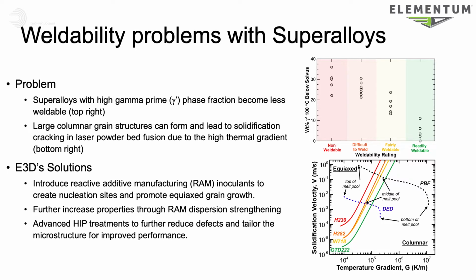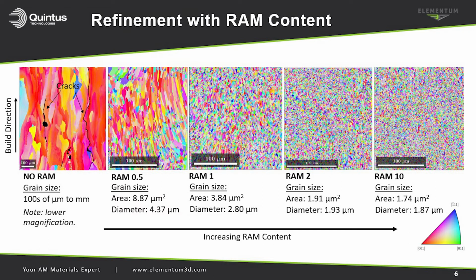There's surface treatment approaches. You can use chemical, mechanical polishing, or other types of surface treatments to remove the surface cracks. But one of the ways Elementum's been focusing on dealing with this is through modification of the alloy. So for alloys like the alloy 230 that's suffering from the solidification cracking, we've been able to shift the columnar equiaxed transition curve for that alloy with our RAM process by forming inoculation sites during the solidification process. And so that allows for a more equiaxed, fine-grained microstructure that doesn't suffer from the same solidification cracking problems that the traditional alloy does. And now we found that combined with a Quintus HIP process provides even further performance benefits.